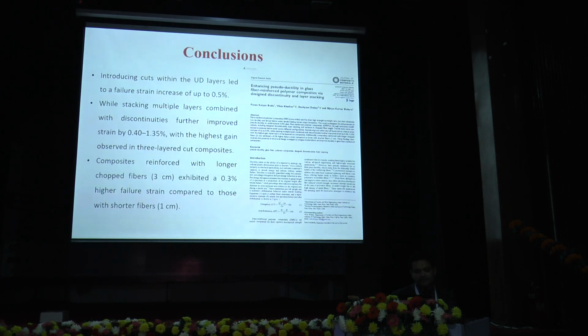This article we have already published in the Journal of Composite Materials. Introducing cuts within the UD layer increased the failure strain up to 0.5%, and while stacking multiple layers combined with discontinuities, we improved the strain up to 1.3%, with the highest gain achieved in the 3-layer cut composites.